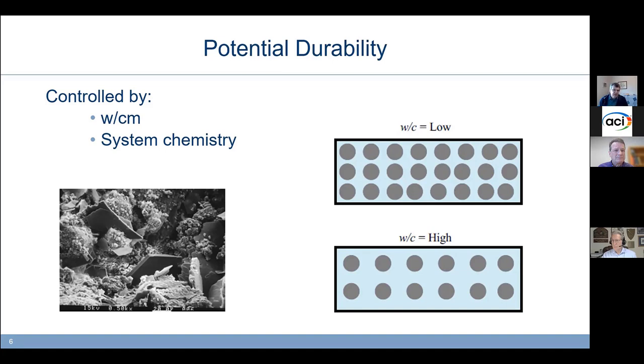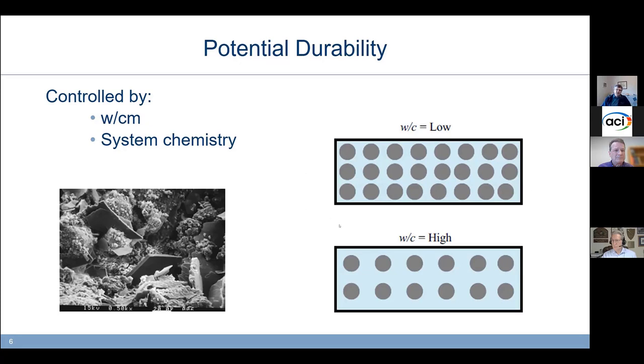The other lever is the cement chemistry. Modern cements create a lot more calcium hydroxide — hexagonal-shaped crystalline plates. These are not necessarily deleterious; they keep the pH of the system high, which protects reinforcing steel. But they are negative in that they are the first in the paste system to dissolve in acids or soft water, and they also provide a planar weakness. Cracks are more easily propagated through these flat, smooth shear planes rather than through the complex system of calcium silicate hydrate fingers. So controlling the chemistry to limit calcium hydroxide and reducing the water-cement ratio are the two fundamental levers for ensuring durability.